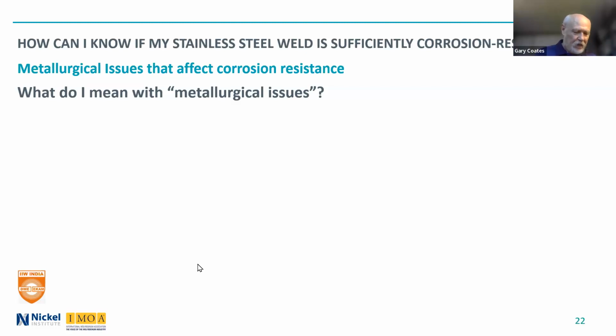We were involved in an offshore project in Canada where it was seawater piping. They were using the 6% moly stainless steels, and their spec called for pickling and passivation, but the corrosion specialist with the offshore engineering company said, yeah, I know, if you pickle it properly, you don't need to passivate afterwards. So he wrote it off. We didn't have to do the passivation on the welds after pickling. We just made sure that the pickling was done properly.